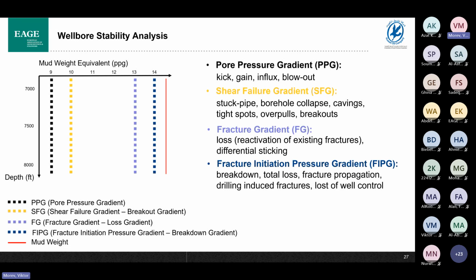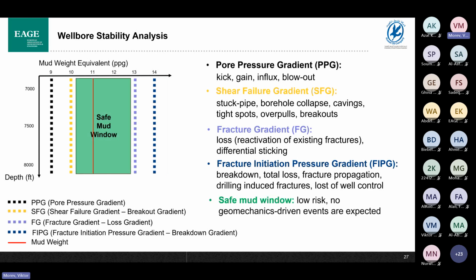It typically results in total loss and fracture propagation. On the microimager, we might see the drilling-induced fractures, and the whole situation may end up with loss of well control. So the only area on this plot where we must keep our mud weight is called the safe mud window. This area has a lower risk, and no geomechanics-driven events are actually expected. So we will try to keep our mud weight within the safe mud window.